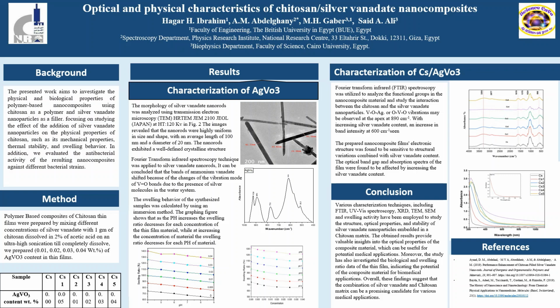Fourier transform infrared spectroscopy was utilized to analyze the functional groups in the nanocomposite material and study the interaction between the chitosan and the silver vanadate nanoparticles. In the spectral range of 400 to 4000, thin films of pure chitosan and other samples of mixed chitosan with various mass fractions of silver vanadate were assessed. With increasing silver vanadate content, an increase in band intensity at 600 cm⁻¹ was seen.